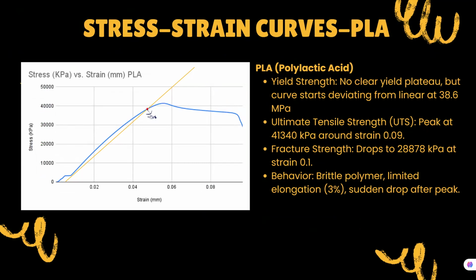And we can see that the yield strength here is 38.6 megapascal. There is the red dot here. And then the ultimate tensile strength, the highest point, is 41,340 kilopascal. And for the fracture, the end here, after it dropped to 28,878 kilopascal. And PLA here has the behavior of a brittle polymer, and we can see the elongation is very small.